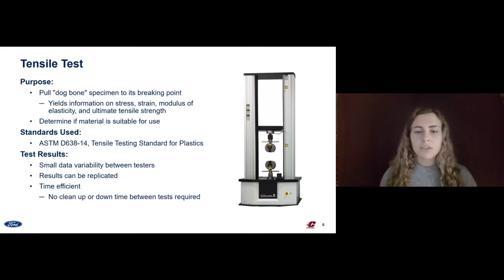These values are used to determine if the material has been thermally degraded, or in simple terms, if the material is good or bad. Ford uses the ASTM standard for tensile testing to ensure that each employee is conducting the test the exact same way. This standard lists the procedure, preparation, and calculations needed to perform this test.